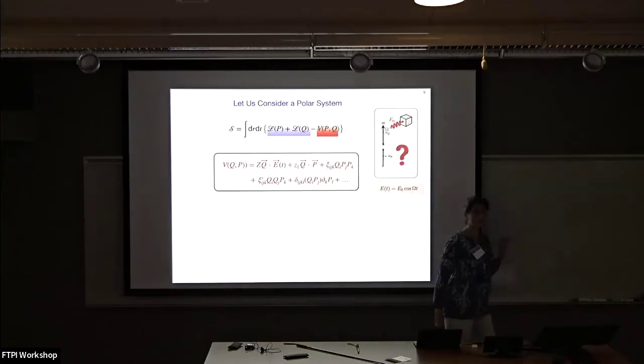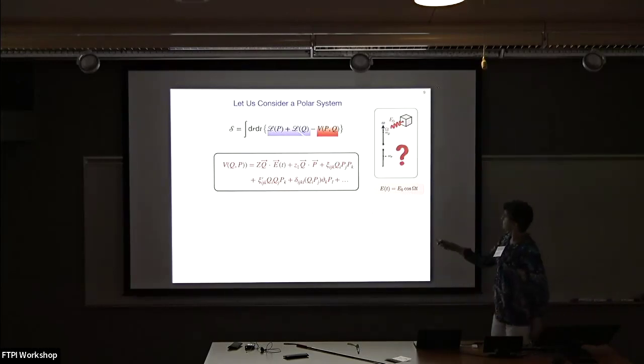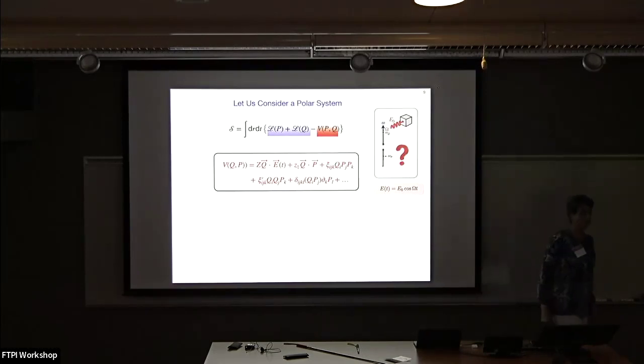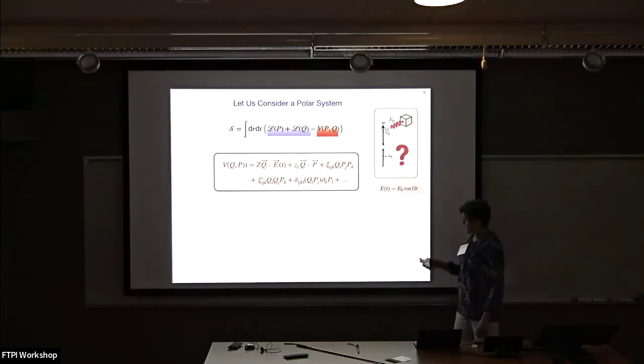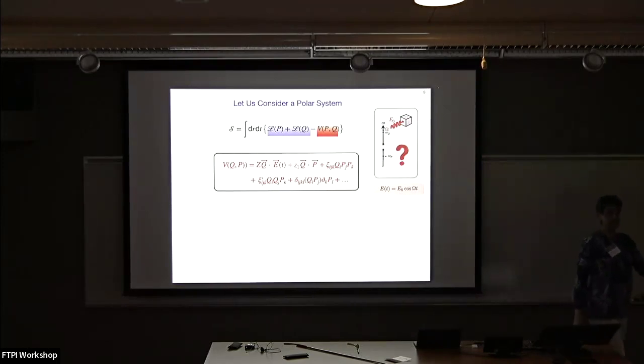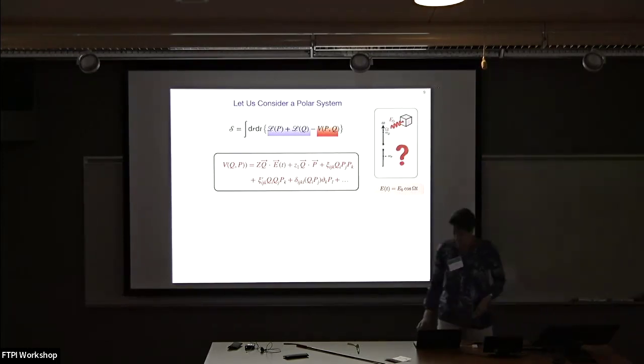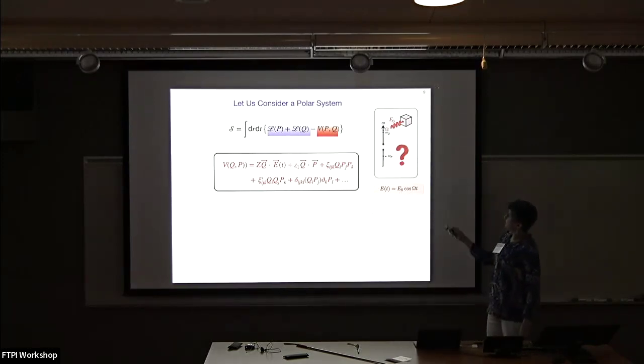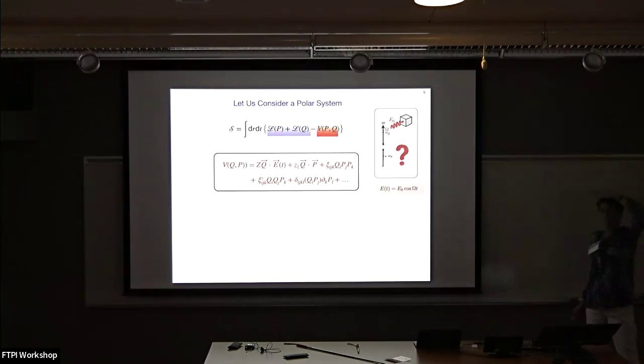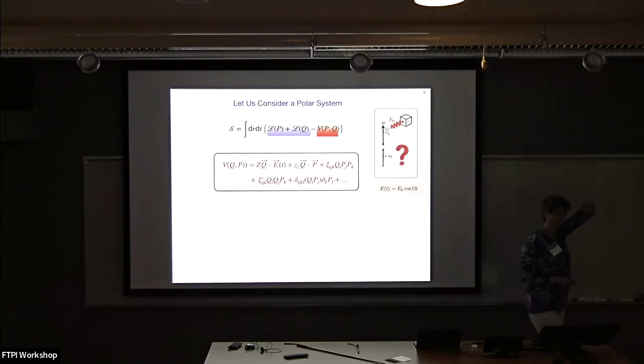Now, if I have inversion symmetry, then these terms are 0. And I have a term that looks a lot like a term that Peter was talking about before. However, I'm in broken inversion symmetry. I have a polar axis. So for the moment, this is a subleading term. I'm going to align my electric field with the polar axis. And because I'm resonantly driving, this term will not be important because it's at very high frequency. Remember, we're interested in what's going on below the drive frequency, so we're not going to worry about this term.